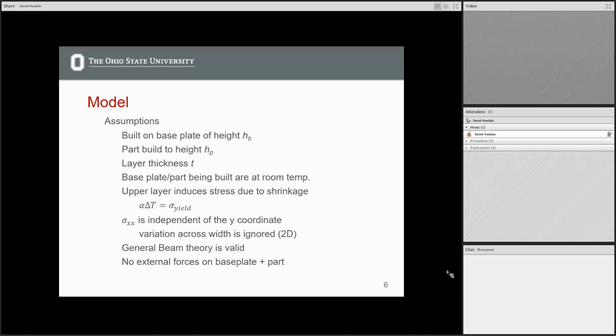We're going to assume that the base plate and the part are both at room temperature, and that the upper layer induces this thermal stress due to shrinkage, and that's going to be equal to the yield stress of the material. Then we're also going to be able to say that the stress that we're concerned with is independent of the thickness or the y direction of our part. So we're going to be concerned with a 2D model that has coordinates in the z direction, which is the build direction, and the x direction, which is along the length of the part.